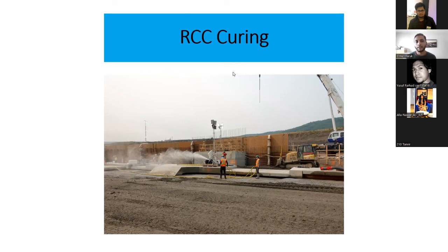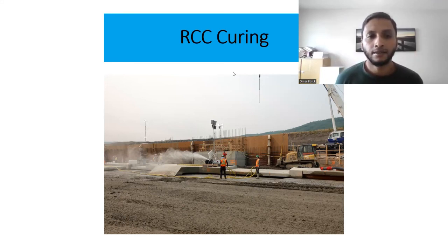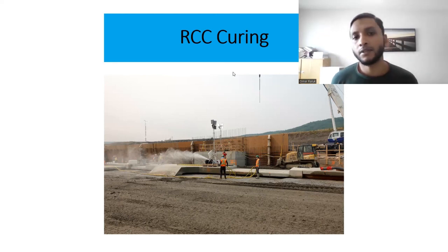That is the first dam where we used cooling lines inside the structure, into the mass concrete. Cooling lines are PVC pipes. We just flow cold water through the lines, and we design it in such a way that we can cool down the structure. So the faster we can cool down the inner concrete, the quicker the strength generation will be, and then we can open it for normal use or for whatever purpose the structure was built for.